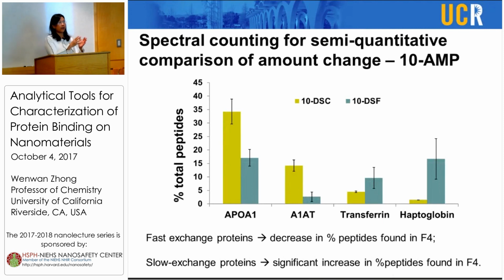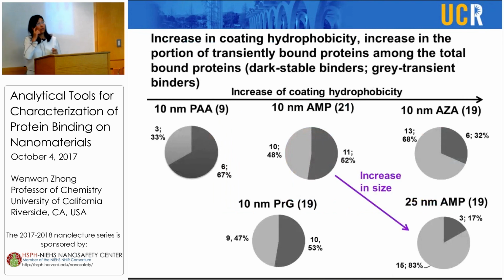So that's why we use the semi-quantitative method to confirm that what we identified is actually the depleted. We could indeed identify both the hard and soft corona, and we can also do spectral counting to confirm some that are not completely removed but still have some remaining in the F4 portion, but have fast kinetics. So what we found is that if the hydrophobicity of the particle surface increases, then the proportion of the soft corona also increases, which is the light gray part on this pie chart. And also when the size increases from 10 to 25 nanometers, we see an increase of the soft corona proportion.